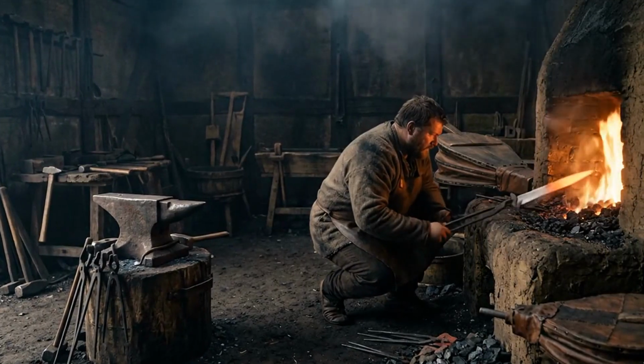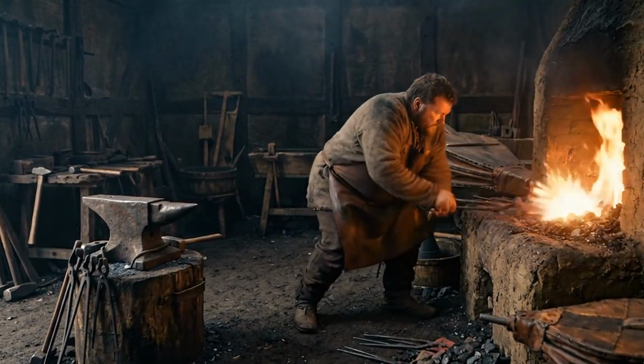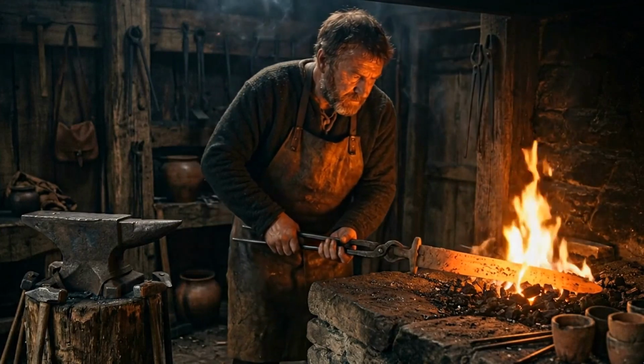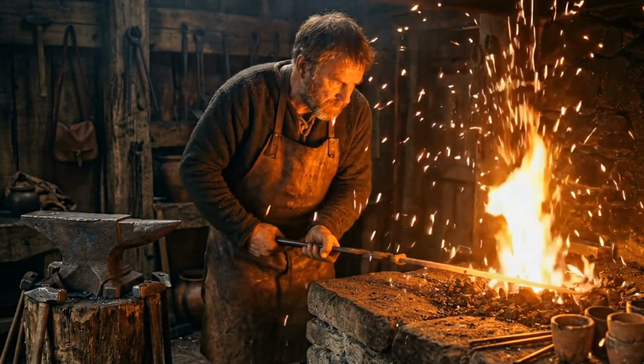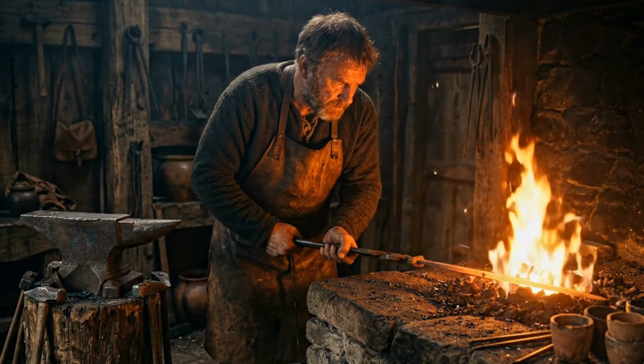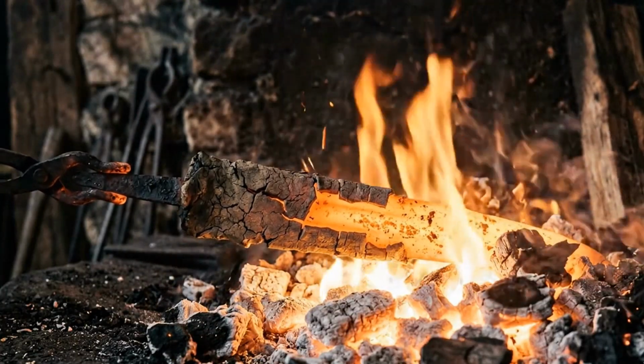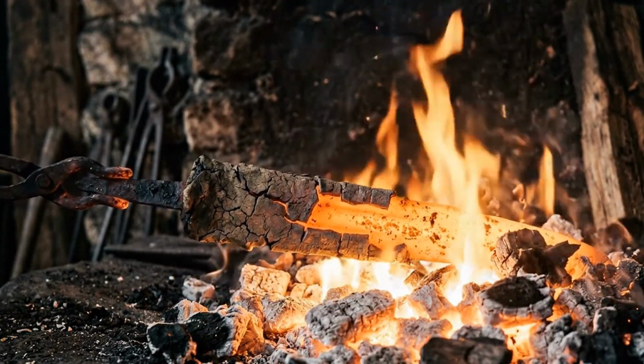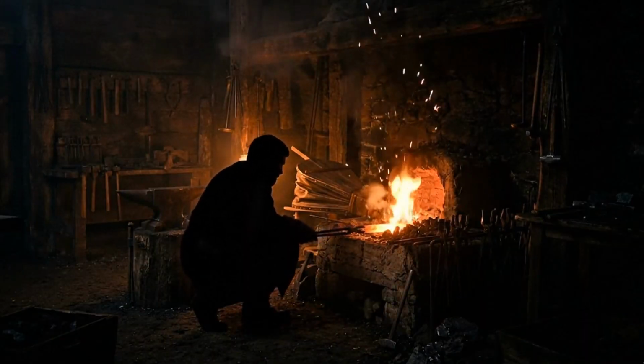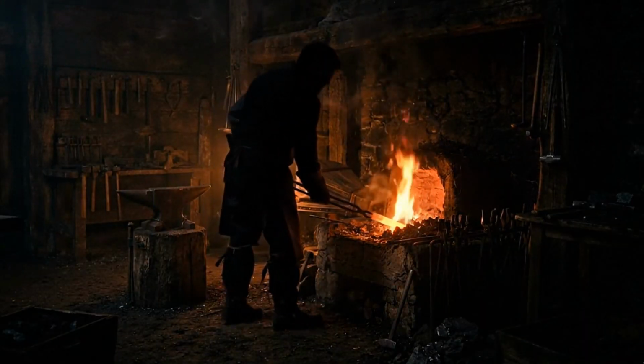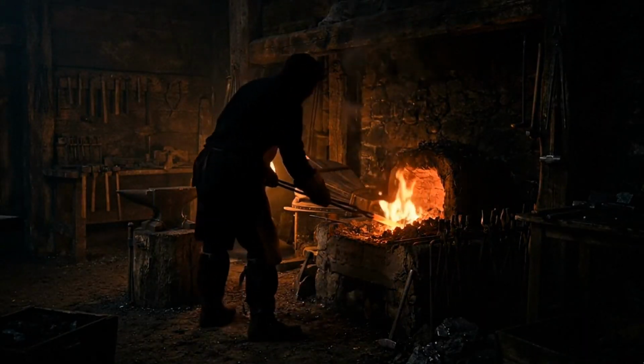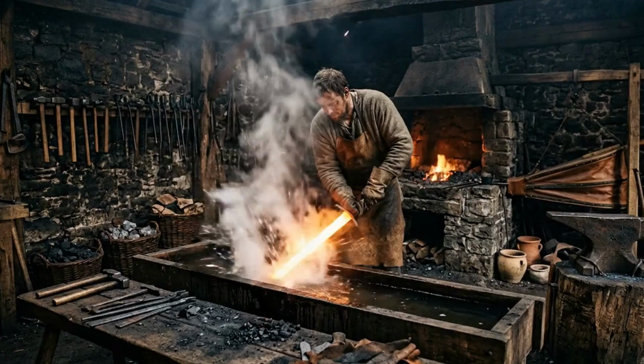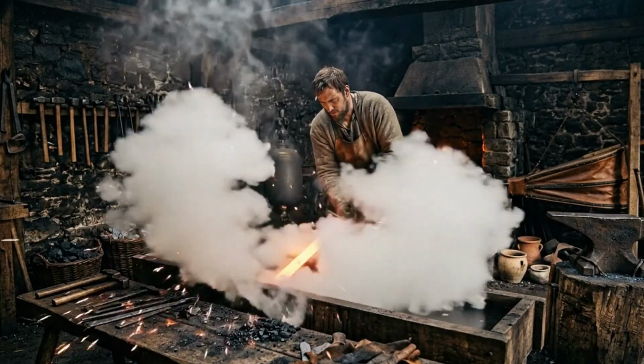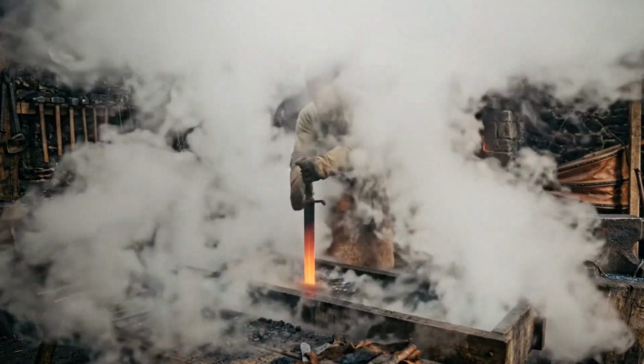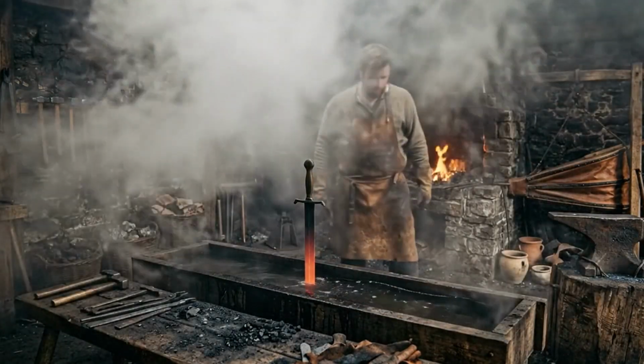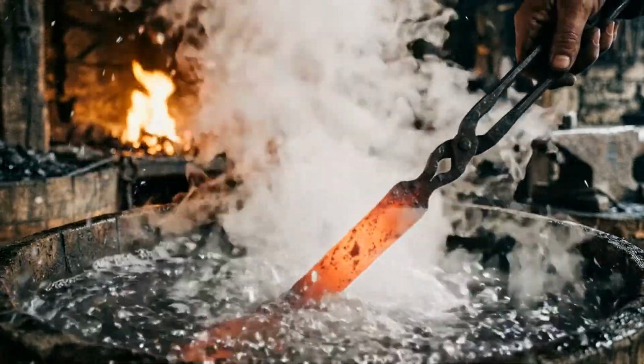The clay-coated blade was placed in the forge and brought to a precise temperature, typically in the range of 750 to 800 degrees Celsius for high-carbon steel, judged entirely by the color of the glowing metal in the dimly lit forge. Many smiths performed the yaki-ire at night or in a darkened room so that the color of the steel was not distorted by ambient light. When the blade reached the correct temperature, the smith removed it from the fire and plunged it edge first into a trough of water. The quench was violent and immediate.